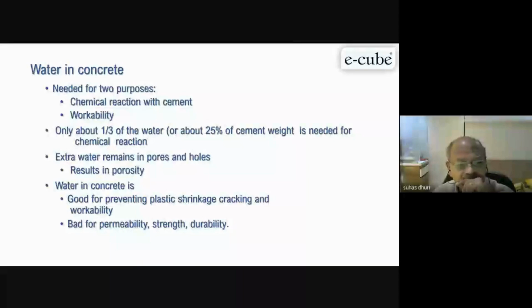So there you adjust your water requirement, because cement cannot be changed. If one bag has gone, we know it is 50 kg. So water has to be controlled at optimum content for the required workability. That one has to understand and proceed for concrete production. It's very, very important. Otherwise, you get a very highly permeable mix, strength is lost, and you also lose durability.